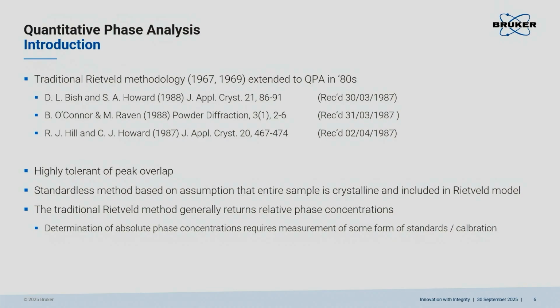Very important. So what is important about the Rietveld method? Highly tolerant of peak overlap. It opens you a huge range of applications which you cannot do with single peak fitting, or with single peak methods, I should say. It is standardless. That is also very important. However, it has an issue, and we will come to that later. The Rietveld method, at least the traditional Rietveld method, can only produce relative phase content. This is important to keep in mind.